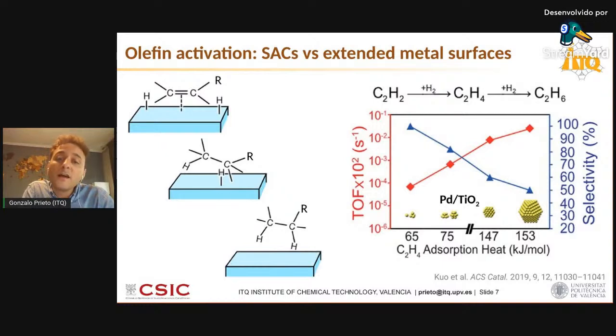As you can see here, olefins, so the alkene intermediate product, bind way less strongly to single atoms than they do to extended metal surfaces in nanoparticles and clusters, which are those catalyzing this undesired further hydrogenation of the alkene to alkanes with orders of magnitude higher turnover frequencies, or reaction rate per unit metal center, compared to the isolated metal centers. So isolated metal centers are not very effective in pi coordinating, activating olefins, and at the same time activating hydrogen to insert into alkyl metal bonds and therefore drive undesired premature hydrogenation, which is something to certainly avoid when the goal is to functionalize your olefin.